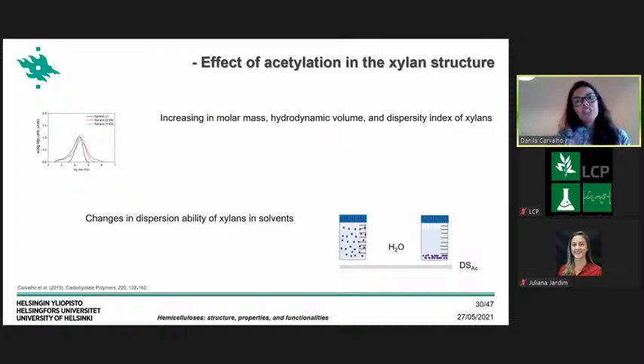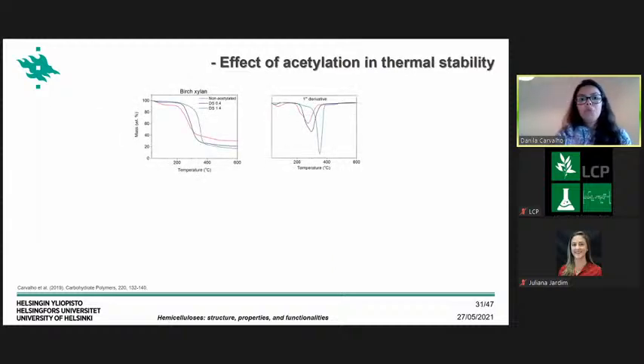The acetylation, of course, changed some properties of the xylan. It increased the molar mass, the hydrodynamic volume, and the dispersity index, and also changed the dispersion ability of the xylan in different solvents. By the acetylation, the xylan became less prone to be dispersed in water, for example. But probably the main result of this acetylation was in terms of thermal stability.